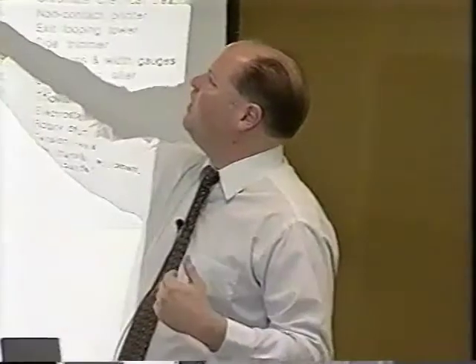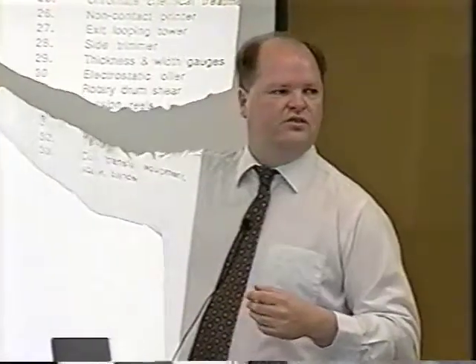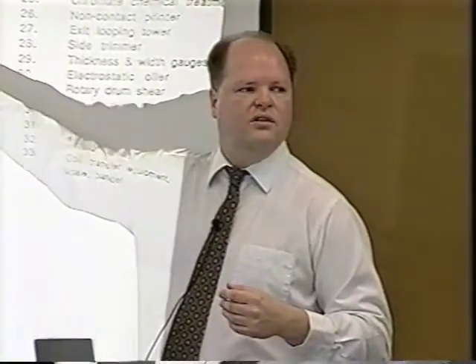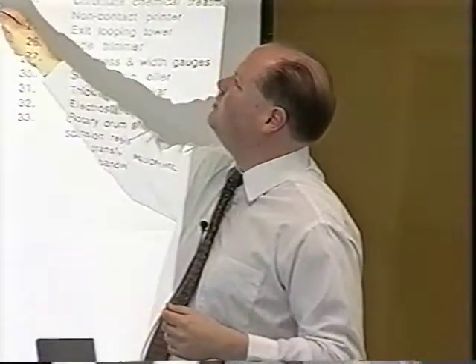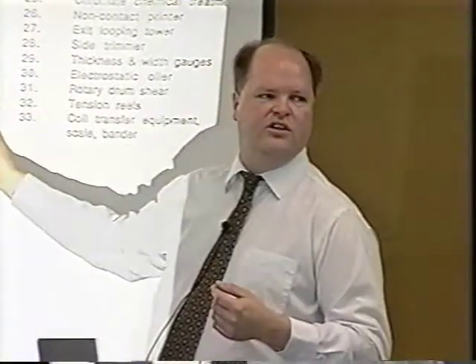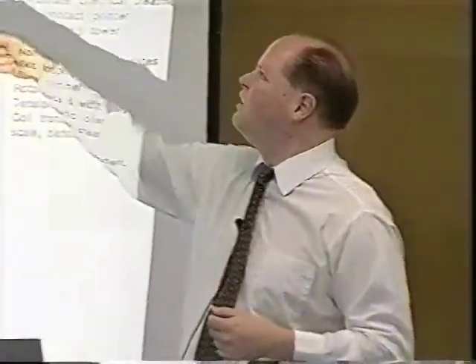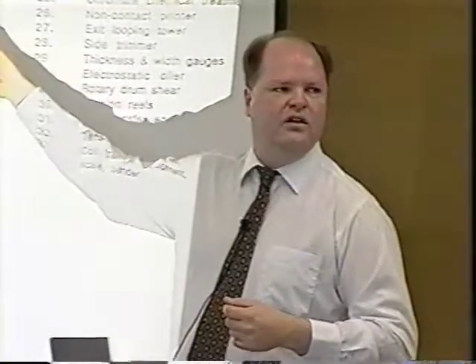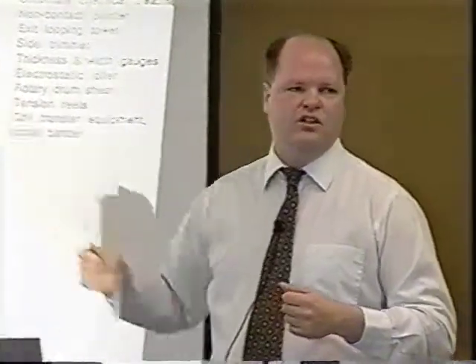Yes? Does that heat affect the annealing or the hardness of the metal? Well, we're kind of taking account of all that because in our annealing furnace here, you're kind of heating it up a little bit more, but you just annealed it, it's still 800 degrees here, so you're not affecting it anymore by annealing it here. No, it shouldn't change the properties.